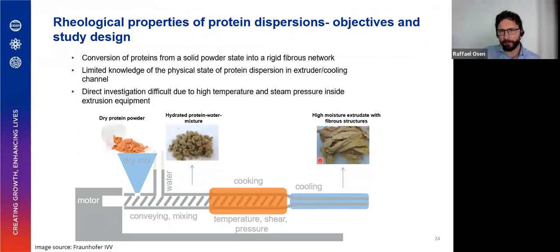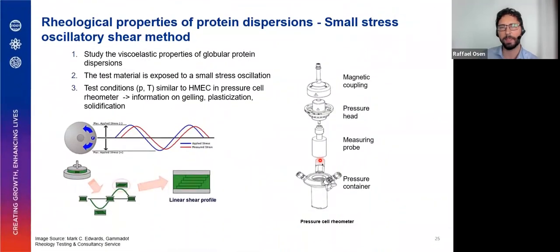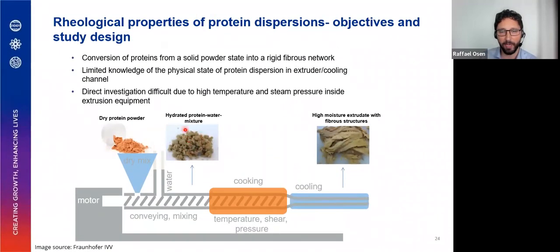Now, in order to develop a certain structure of extrudates, a certain lengthwise or crosswise fiber structure that can then be used in different meat products, pork, chicken, or beef, it's important to understand the rheology, the viscosity, the flow profile during the cooling die. And this is all, again, affected by the protein structure. So one way to better understand what is going on during the extrusion and during the cooling die passage would be to do rheological tests. Now, the challenge here is that the materials, as can be seen in the graph below, usually form a very crumbly dough-like structure at a protein concentration similar to what we have during extrusion. So it's difficult to do a viscosity test.